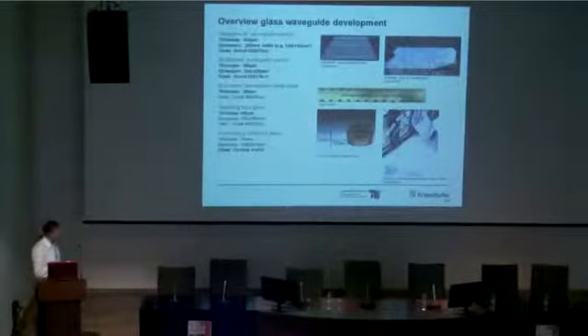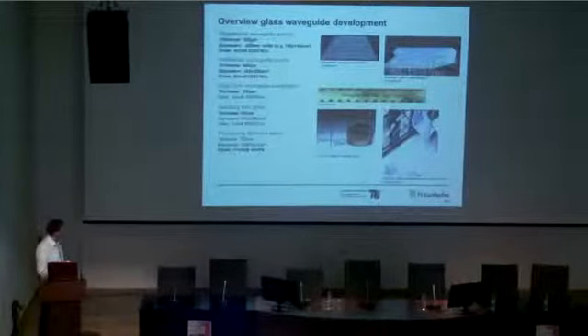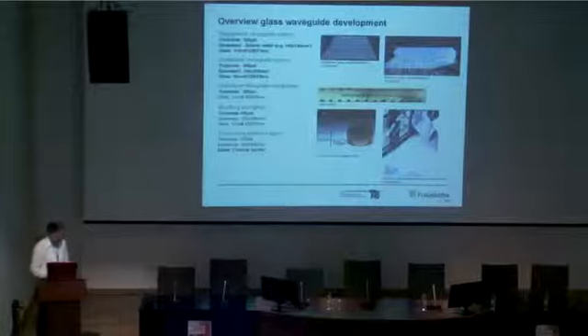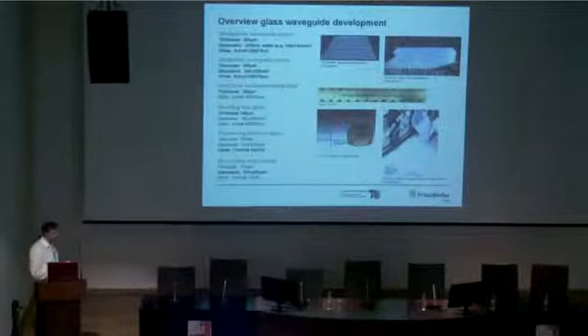For instance, we studied another glass, the Corning Gorilla glass, and it shows that we can improve the propagation properties. The propagation loss was decreased in this kind of glass. And we are also looking at increasing the panel size. At the moment we are upgrading the whole process line so that we can process panels in the size of 570 by 420 square millimeters.